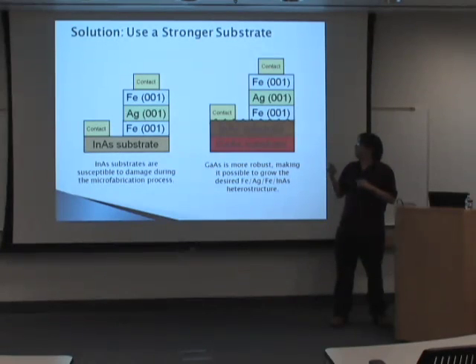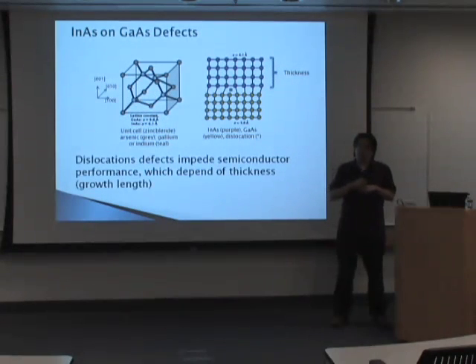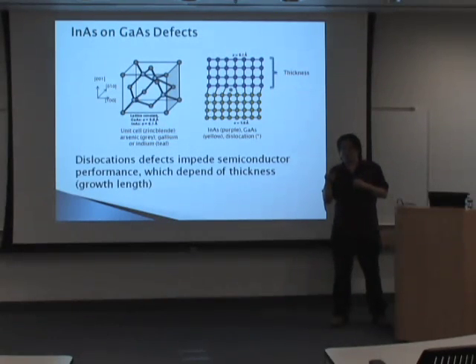And in order to grow a better indium arsenide, gallium arsenide substrate, we have to understand where you get the roughness in the first place. And where you get that roughness is through defects, particularly dislocation defects. And dislocation defects are, as seen by this asterisk, just dangling atoms. And you'll see them visibly on the surface of your material as etch pits.